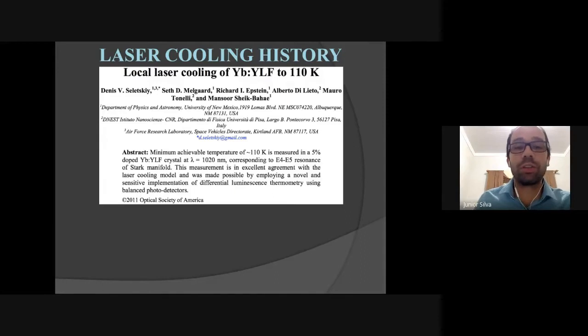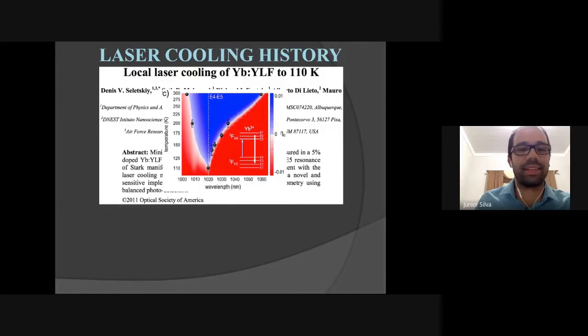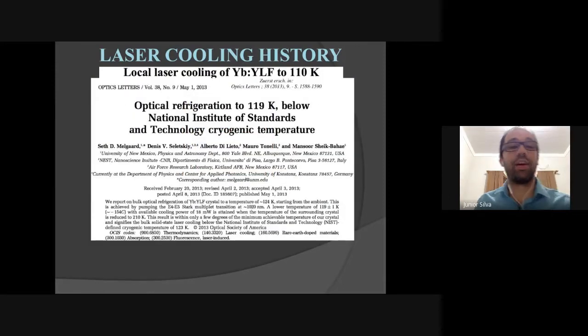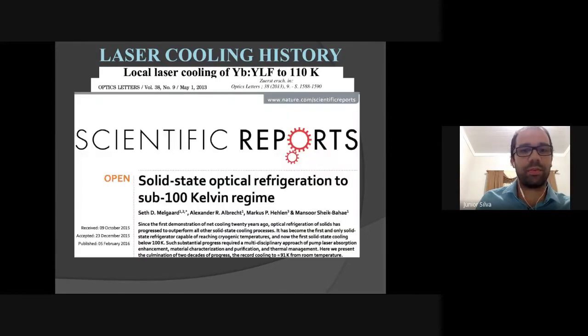This crystal cooled to 110 Kelvin, using ytterbium 3+ ions. This result was an exciting result. And the authors, 2 years later, decided to give big attention to the fact that we were in cryogenic temperatures with a solid state. What's another great achievement? Can go forward. Yes, and in 2016, this material cooled to 91 Kelvin, which is under 100. The first time the solid state cooled under 100 Kelvin.